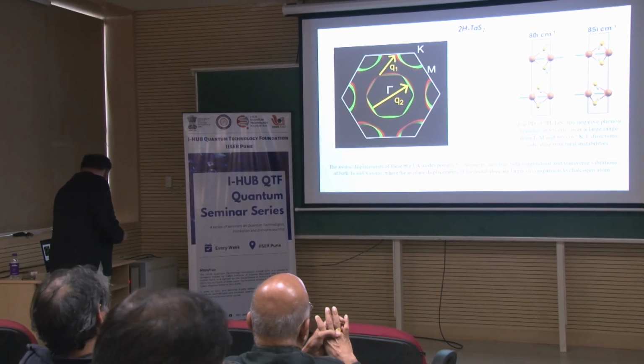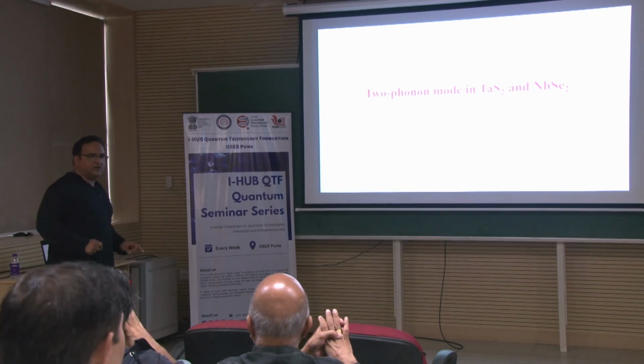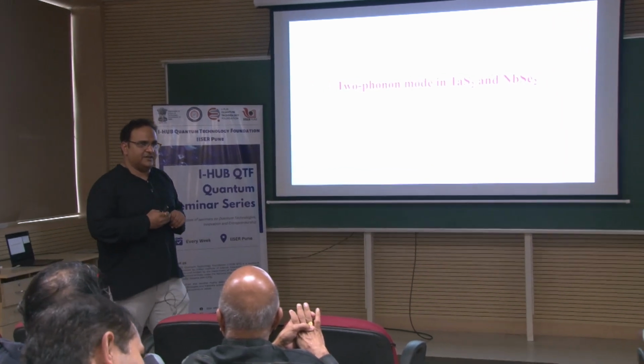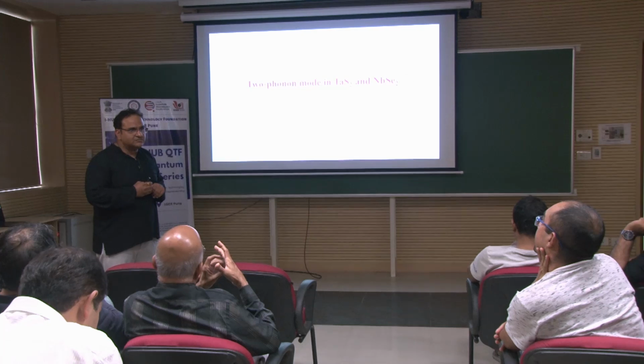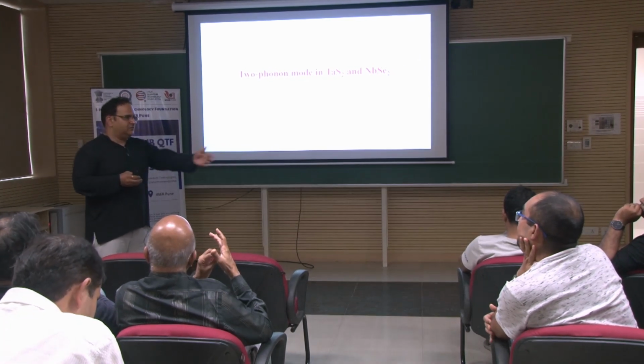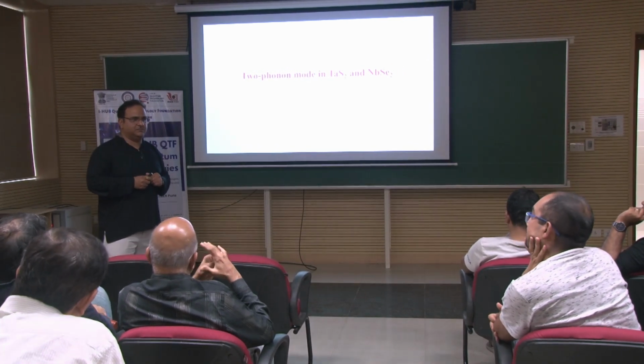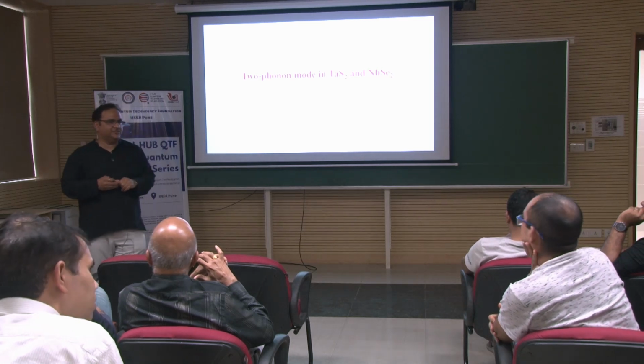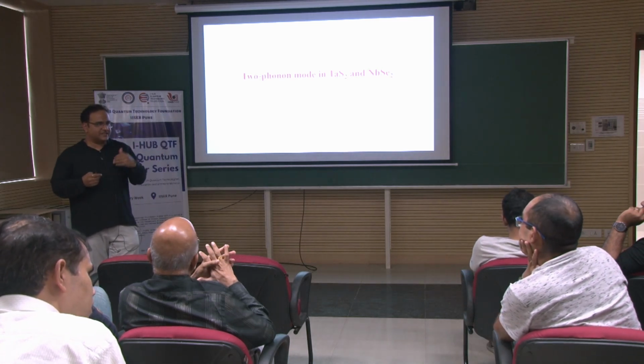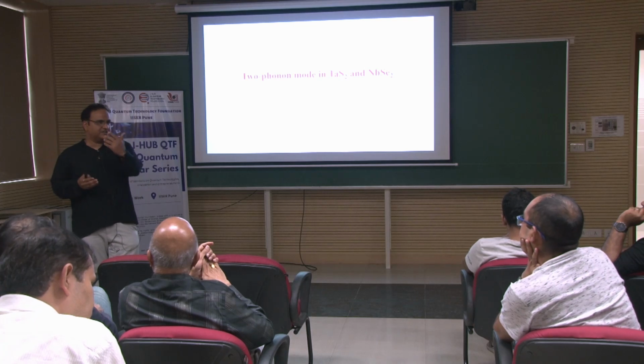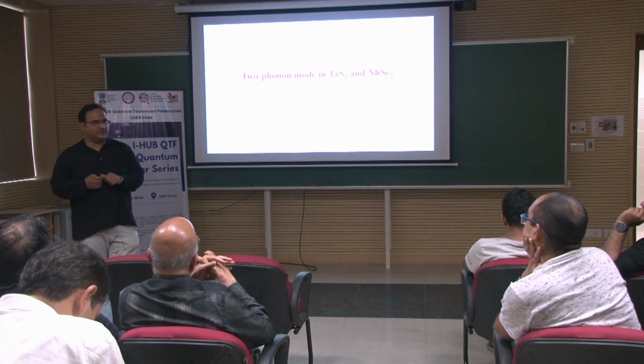So these acoustic phonon modes are not optically active? Acoustics are acoustic. So what is the way then to find their energy experimentally? All the thermal measurements, because acoustic vibrations carry the heat. Brillouin scattering, of course; neutron diffraction is another one.